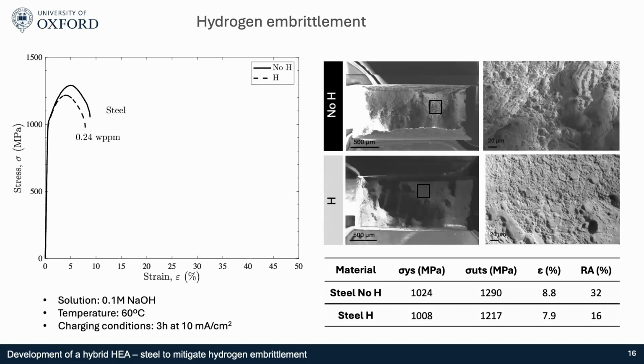So for the steel, after introducing hydrogen for 3 hours, because we did some simulation and it was enough to saturate the sample, we obtained 0.24 weight ppm of hydrogen. And as you can see, there is a slight decrease of ultimate tensile strength. Then looking at the fracture surfaces, in the no hydrogen one, we can see the microvoids. And in the hydrogen one, we can see other flat areas apart from the microvoids. The most noticeable parameter for the hydrogen embrittlement was the reduction in area.